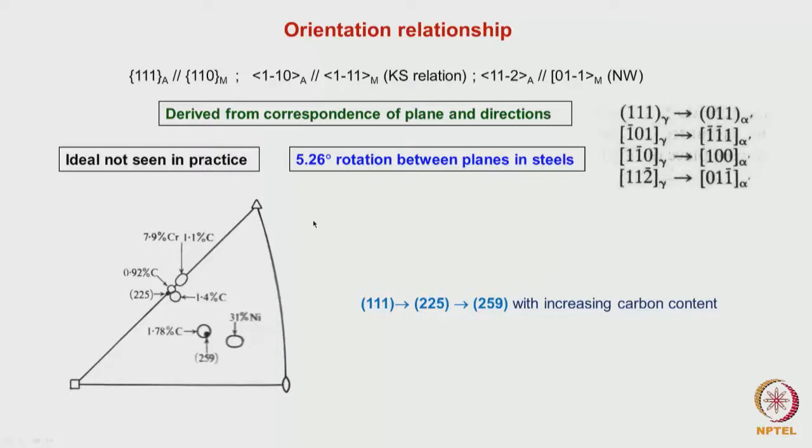Okay. And why do we call this theory a phenomenological theory? The reason essentially is that we do not know what path the transformation takes. The initial and the final ones, we look at, okay, and try to match. The theory is able to explain the experimental observations. Okay.